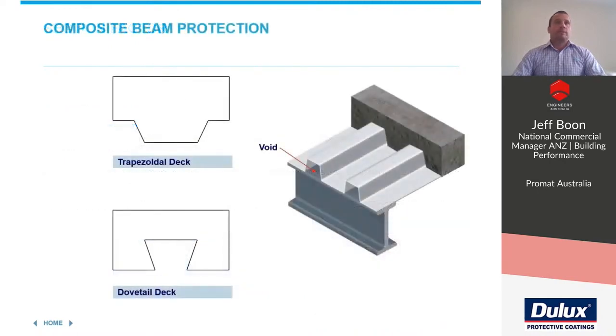Composite beam protection. If a concrete slab is constructed using profiled steel deck, voids are created between the deck and the top flange of the beam. If the void is left unfilled, two potential problems arise. The rate at which the heat enters the section is increased, and the increase in temperature causes the section to lose its strength at a faster rate.